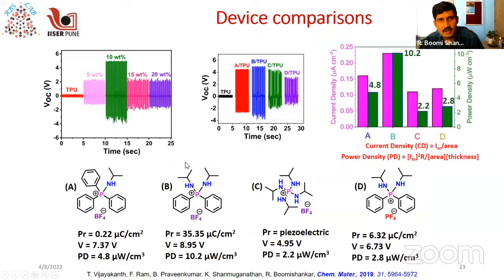Now we can prepare composites with various weight percentage compositions of the ferroelectric material, and we will see that as we increase the loading of the ferroelectric particles, the mechanical or energy harvesting properties increase up to a certain limit, beyond which the performance is lowered. This is because if you crowd the composite with a lot of ferroelectric particles, there is a chance that the particles will crystallize in your system with different directions of dipole. Therefore there will be a randomization of the dipoles present in the system, which will reduce the performance of the material. So you need to always optimize your composition before any measurements.